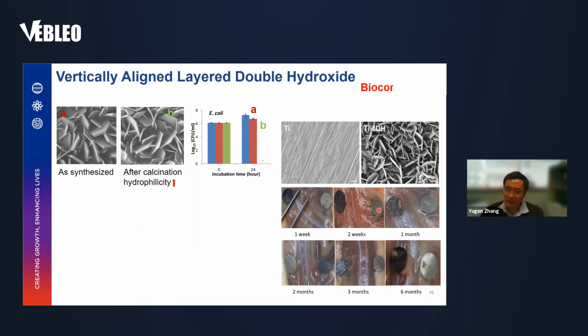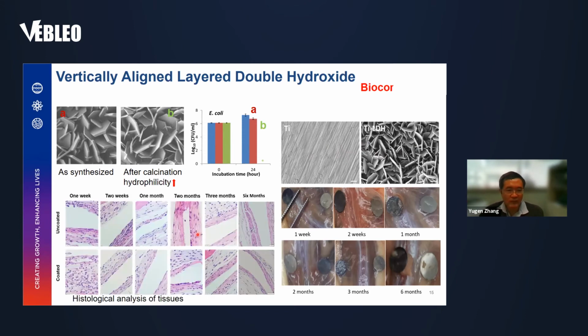And then we put it in vials to do this in vivo experiment. After 6 months, they did not see much difference in the materials from before implant. And also from the histological analysis of tissues, we did not see any difference. And it means the LDH materials grown on the titanium have very good antimicrobial property and also biocompatibility.